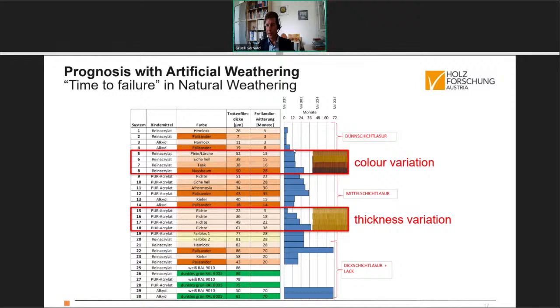The groups of color variation and thickness variation are again shown here. The color variation was not so pronounced here in this test, but the thickness variation brought forward a very nice step here in the results of time to failure.